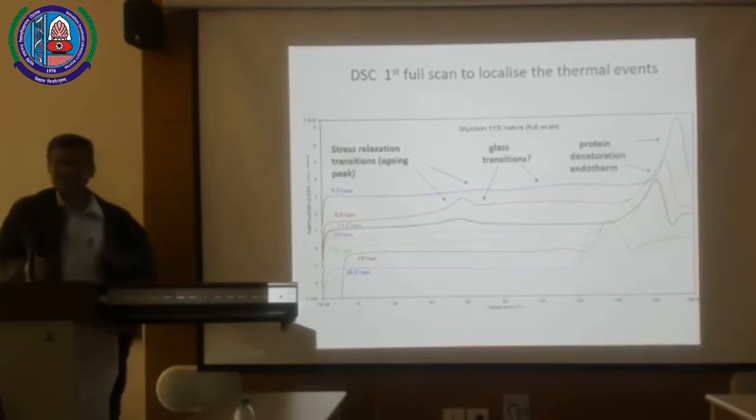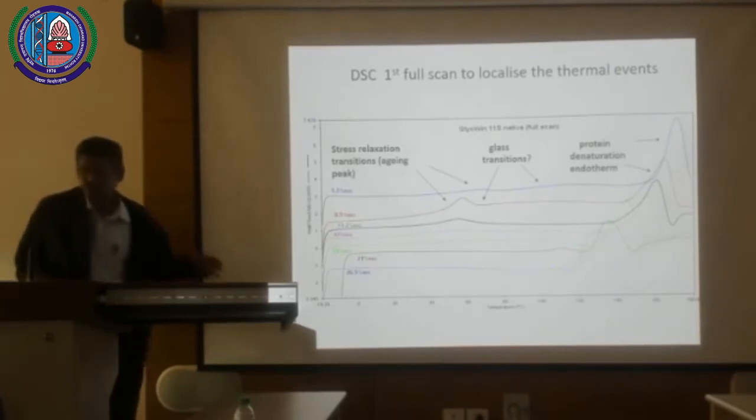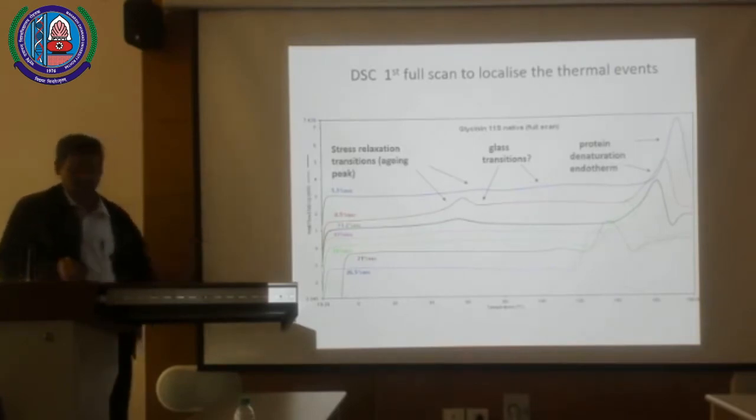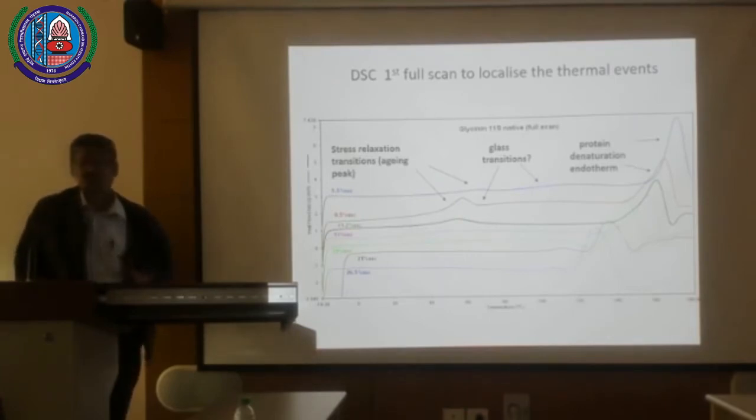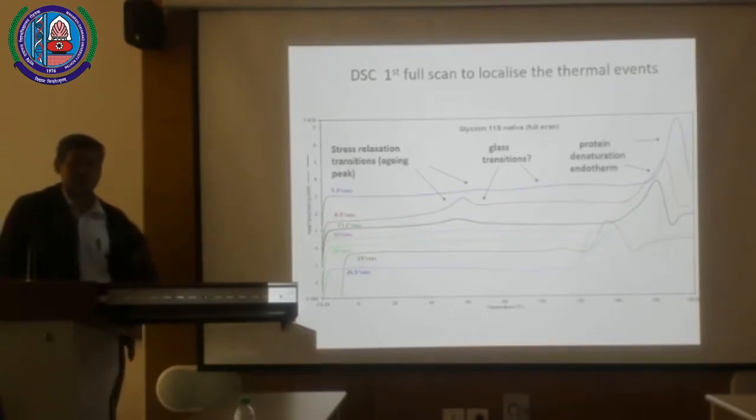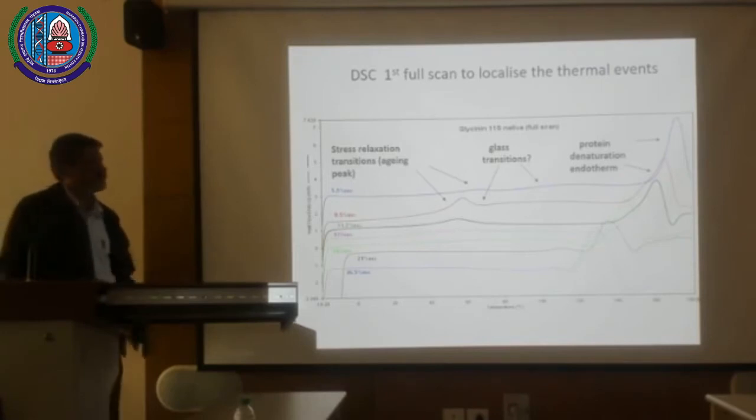If you put it in DSC and take a fresh powder as your control and monitor the same sample, a 2-year-old or 1-year-old sample, this relaxation peak, the Tmax, will be different for a freshly prepared sample and the aged sample, if it has been stored at the same temperature and same condition, coming from the same factory.